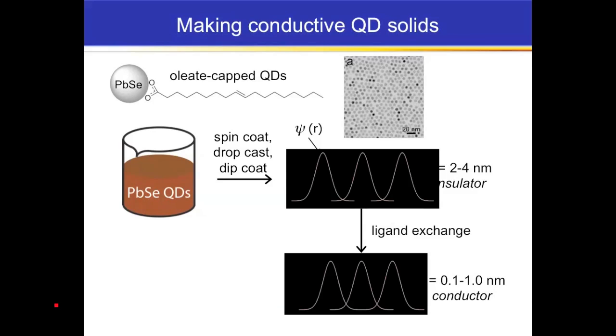OK, so this slide looks a little bit funky, but it shouldn't interrupt my ability to tell the story here. What we do to actually make conductive quantum dot films is the following. We take lead selenide dots that have oleic acid on them. This is inherited from the syntheses. And these dots are about 5% monodisperse. They might be between 3 and like 8 nanometers in size. We take a solution of them.